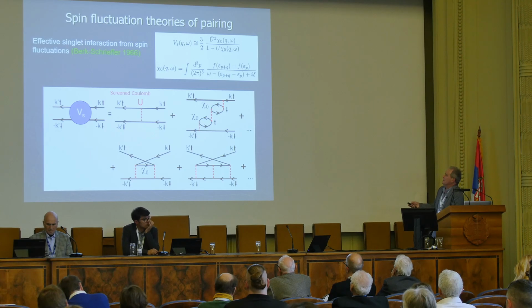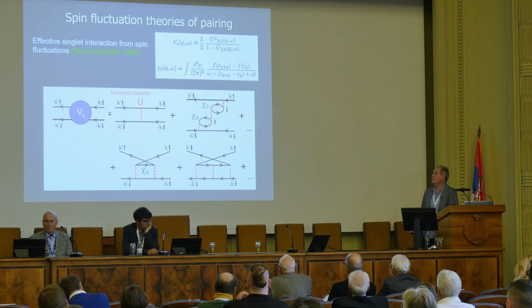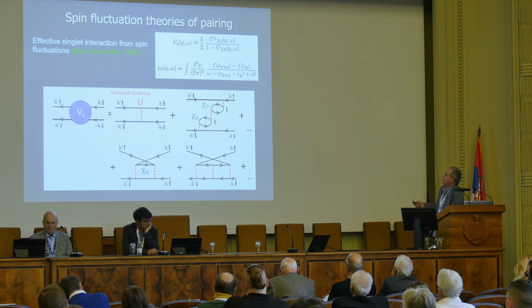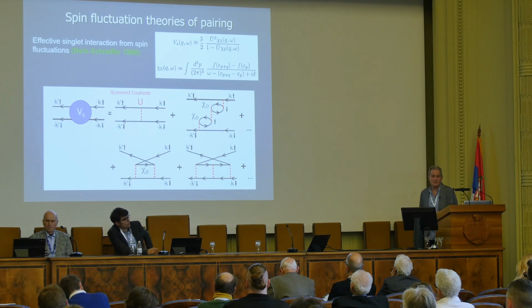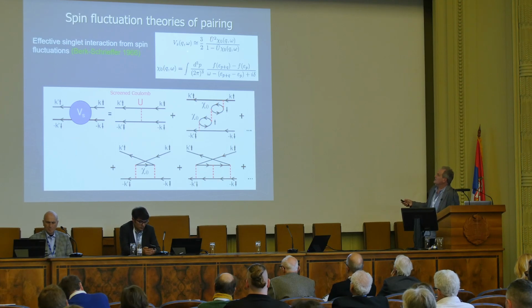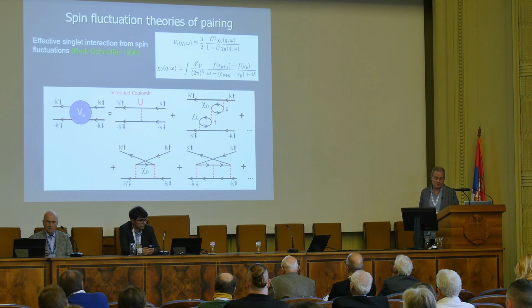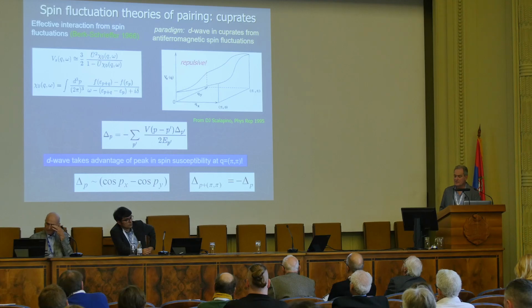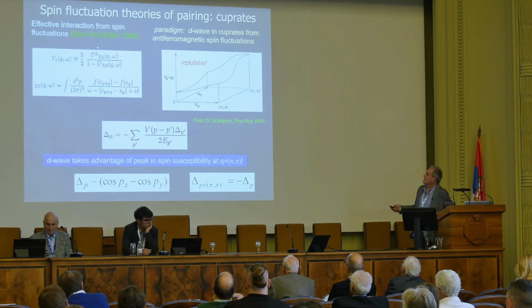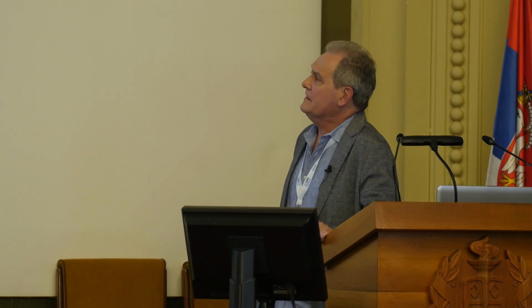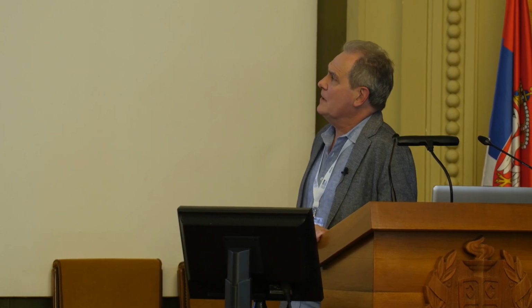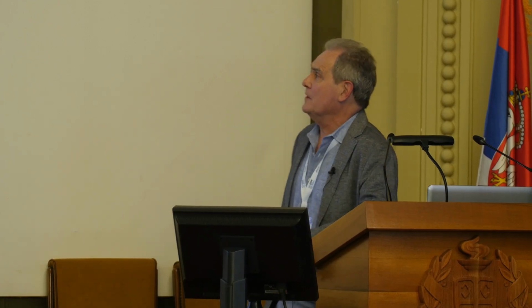You add them up, and some of you will recognize that this has a very similar structure to the Stoner theory of magnetism. In fact, if you look at the right-hand side of this equation, it looks a lot like the Stoner expression for the magnetic susceptibility of a metal with interaction U. It's expressed in terms of chi0, which is the Lindhard function, the response function of the free gas. And the left-hand side turns out to be the effective attraction generated by this mechanism of spin fluctuations. It was done initially for ferromagnetic spin fluctuations, where it's an attraction. But Scalapino and Pines and others in the 90s pointed out that you could use the same mechanism on a lattice instead of with an electron gas to generate antiferromagnetic fluctuation pairing.